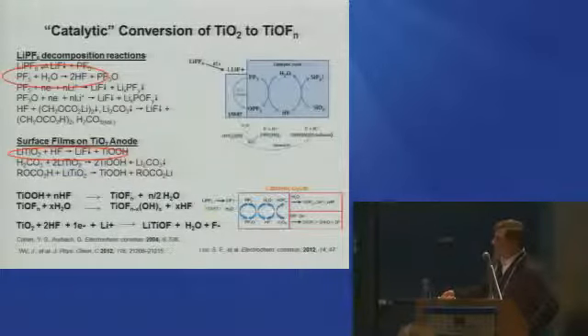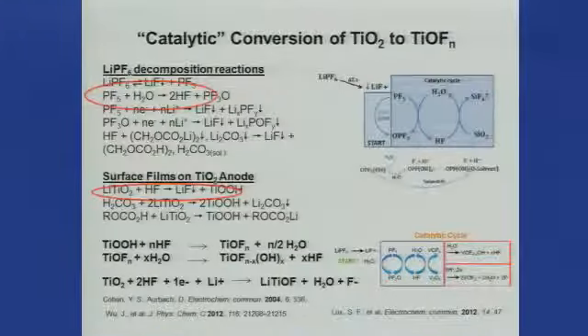But in the presence of HF, you can actually reversibly not only lithiate this material due to the electron transfer from titanium 4 to titanium 3, but you can do anion intercalation due to exchange of the surface hydroxyl fluorine couple. And so this has actually been proposed mechanistically by us in a different context for vanadium oxide. It's even worse, actually. It turns out that this happens at open circuit, where you get bulk formation of these vanadium oxyfluorides. And recently somebody also showed a very similar mechanism for the formation of silicon oxide layers on silicon that then makes silicon fluoride at the surface.